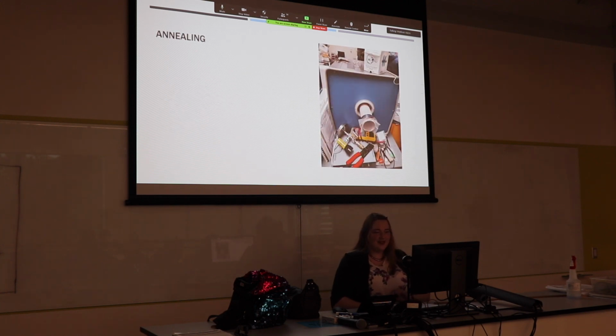Next up was to anneal the film. Now, we used the silicon because that's what our research was over, and we were really hoping that the gallium would diffuse into the film while it was annealing.